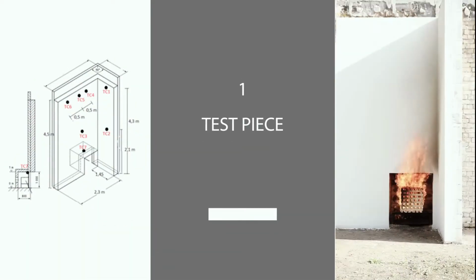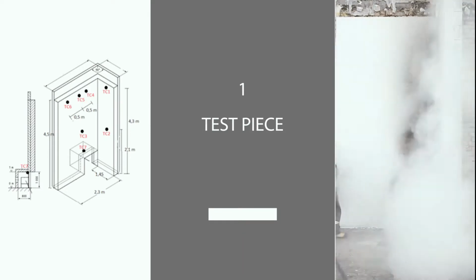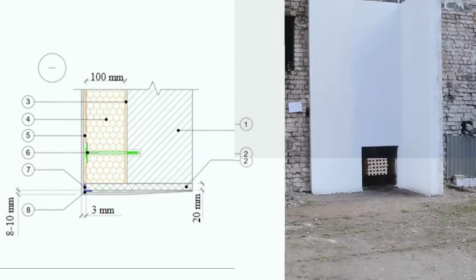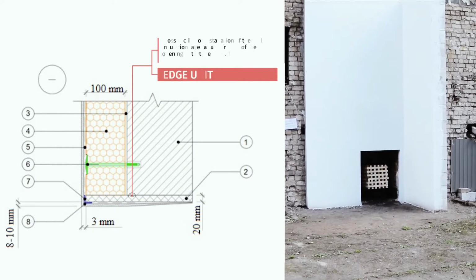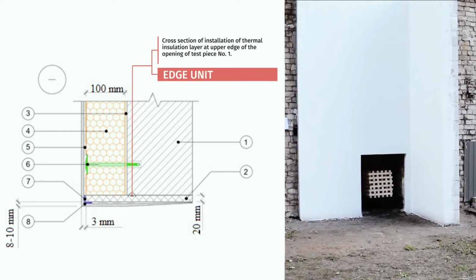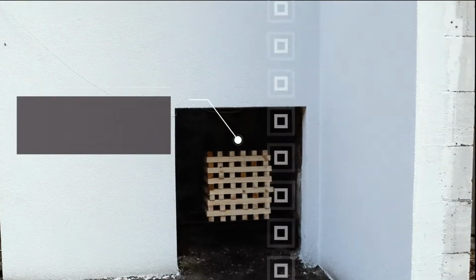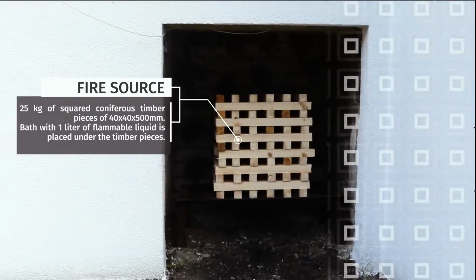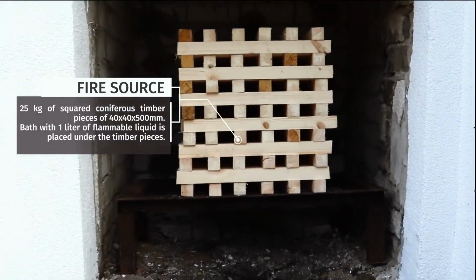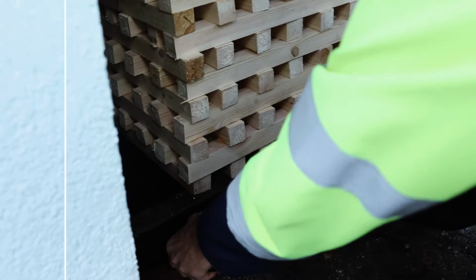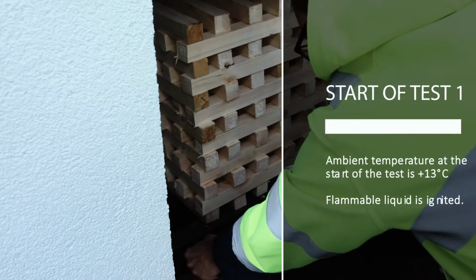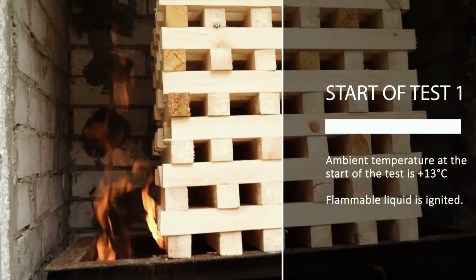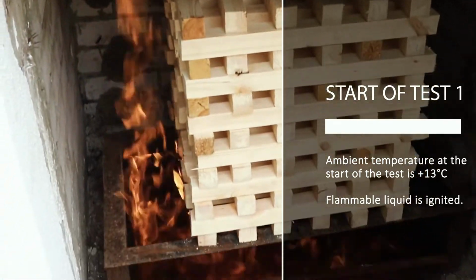First test piece. Cross-section of installation of thermal insulation layer at upper edge of the opening of test specimen number 1. The fire will be produced by 25 kilograms of coniferous timber. Flammable liquid is ignited at the beginning of the test. Ambient temperature is plus 13 degrees Celsius.